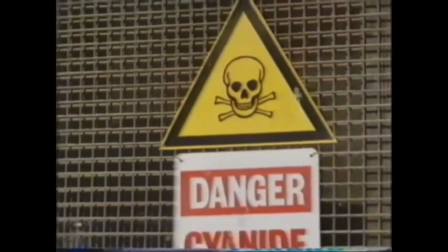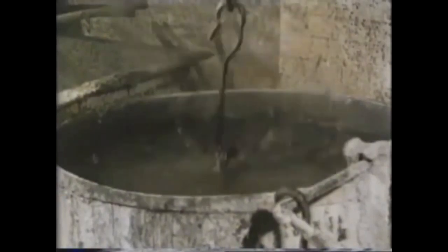It is possible to case harden components without creating such coarse structures. These spindle shafts are made from a low-carbon steel. After preheating, they are carburized by immersing them in a liquid bath of sodium cyanide and sodium carbonate, which also contains a little sodium chloride. They're left in the melt at 900 degrees centigrade for 1 hour. This is time enough to impart a thin carbon case, but not long enough to produce a noticeable grain growth. After an hour, they're quenched in water to give the required hardness to the surface and a clean finish to the component.